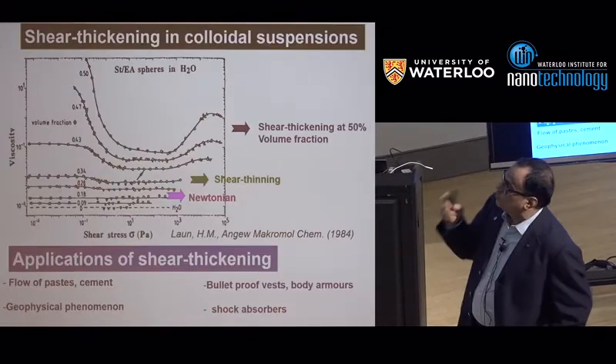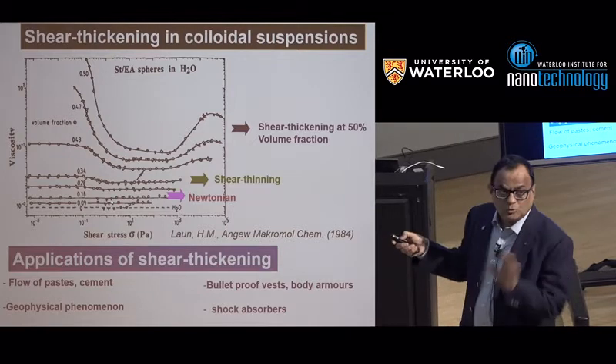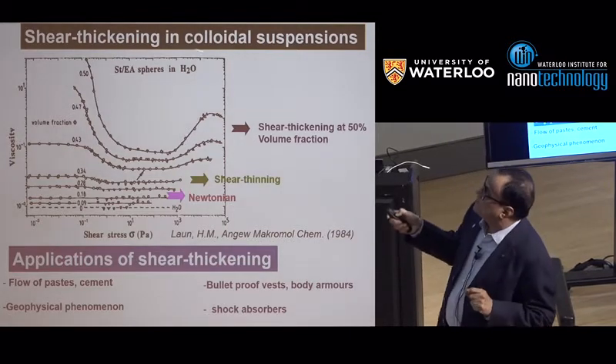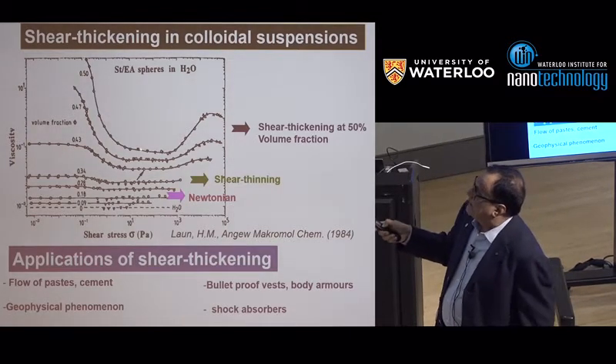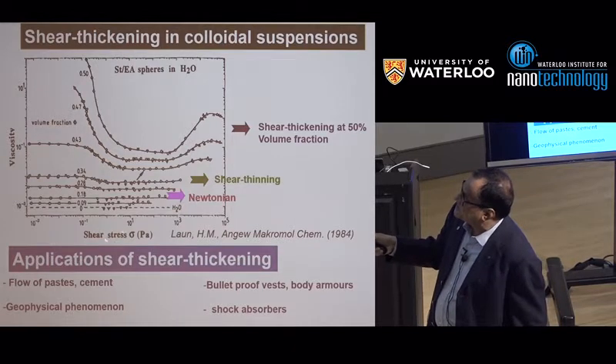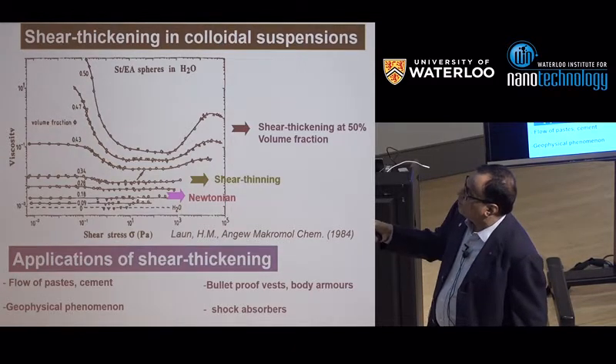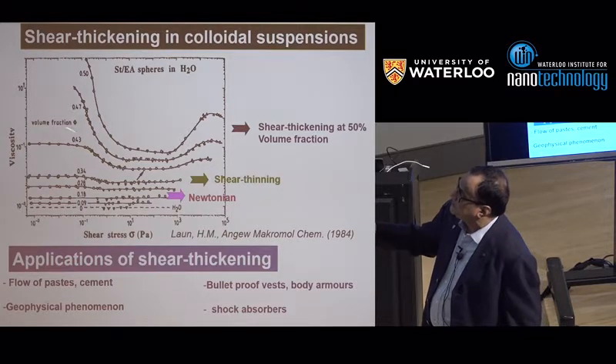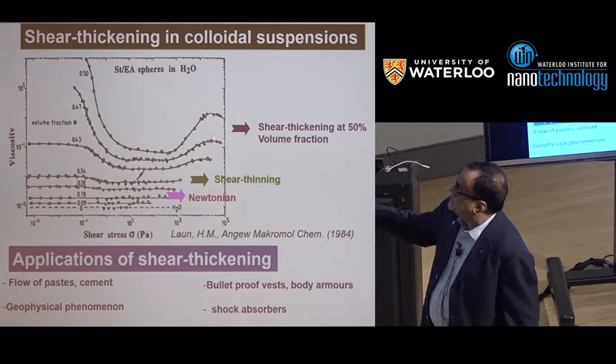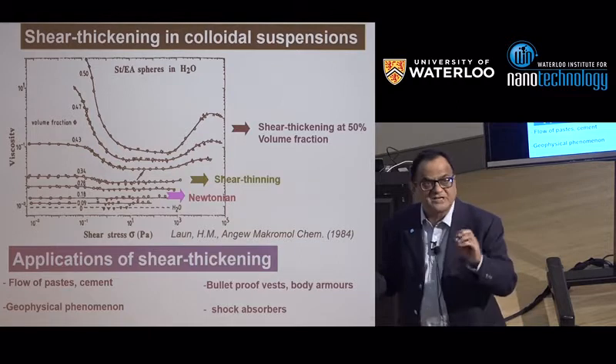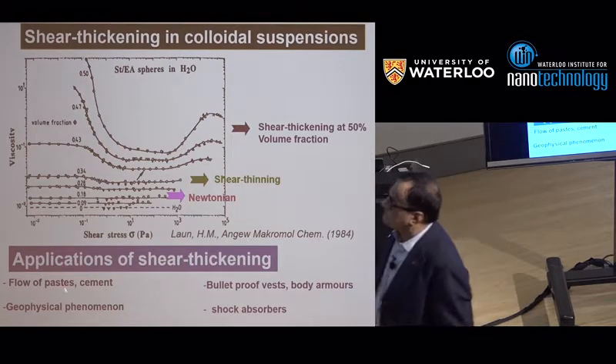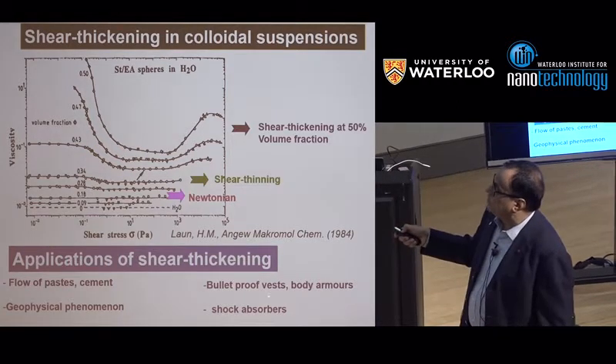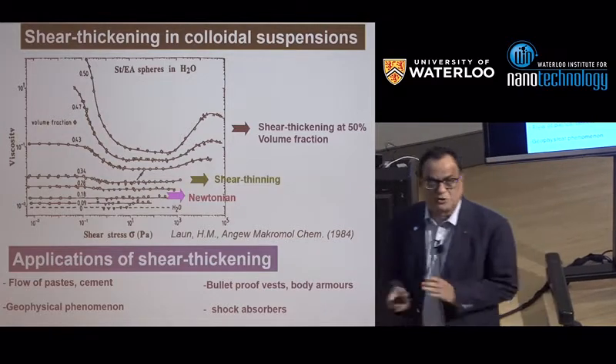So what we showed, so this is something known in the literature, is that if you take silica colloids and plot viscosity versus shear stress, for low volume fraction, it is not very interesting. But above 43%, you can see that viscosity will decrease first at low stress, but now it will increase. And this is the part which is called shear thickening. And this has enormous application in bulletproof vests, body armors, shock absorbers, and so on.